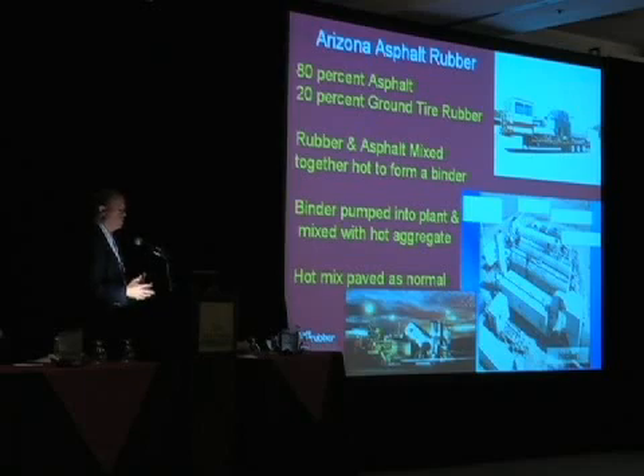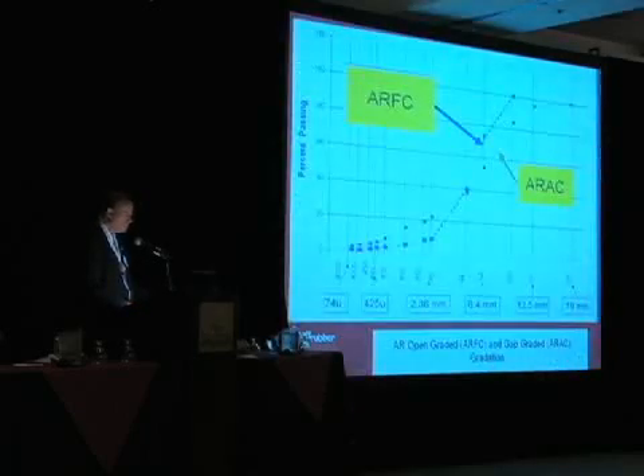When you add the rubber to it, it becomes a somewhat stiffer asphalt at high temperatures. So that's good for preventing rutting, and it also gives you some good cold temperature properties as well. The mixing is a little bit complicated, but not too complicated. A little bit of piping, a little bit of plumbing, a little bit of pumping, and a whole lot of heat. And then eventually you can pave with a normal paving operation.